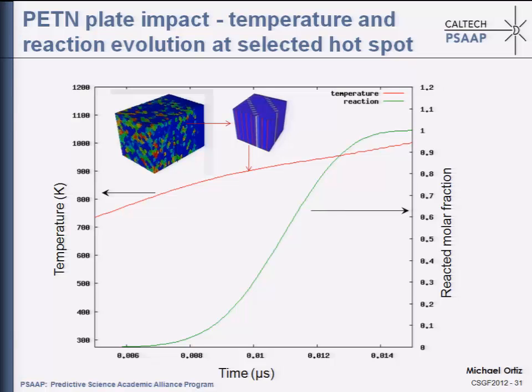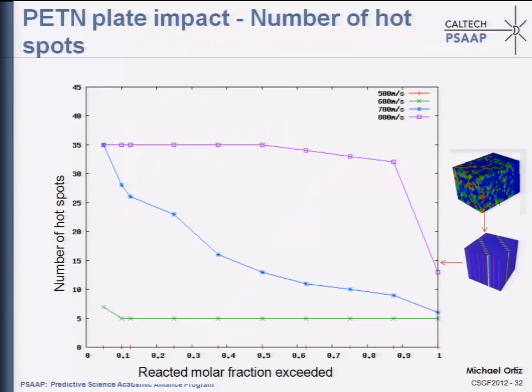So this is the evolution of a typical hot spot, how the temperature rises. This is the molar fraction of a reacted product, showing, in this case, full initiation. And because we have a microscopic model with thousands of material points, thousands of microstructures, we can collect statistics regarding hot spots. So, for instance, you can plot here the number of hot spots where the reacted molar fraction exceeds a certain value. And so you have some handle on the statistics of these hot spots.